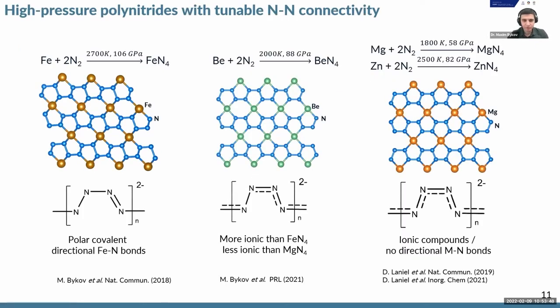And in the case of the beryllium compound, beryllium is more electropositive than iron and less electropositive than magnesium. We have an intermediate situation where we have slightly distorted chains, and we interpret it as a partial electron delocalization within these chains. So the reason for such chain distortion comes from the polar covalent Fe-N bonds in FeN4 compounds. And in the case of magnesium and zinc compounds, we are dealing with purely ionic compounds with no directional metal-nitrogen bonds, which allows the nitrogen chain to lock into the most stable configuration.